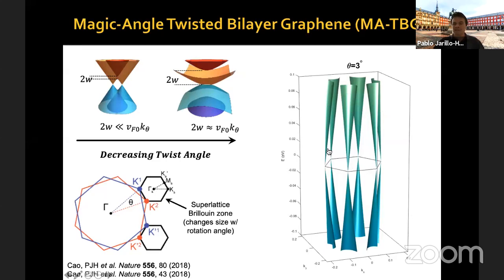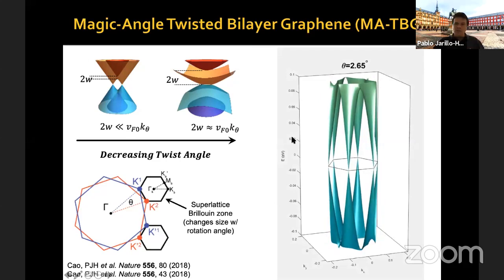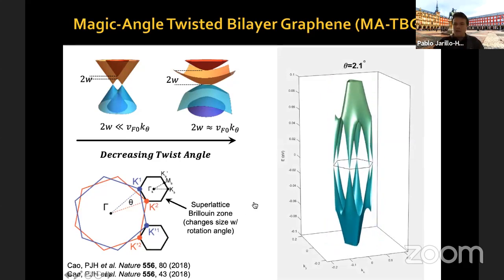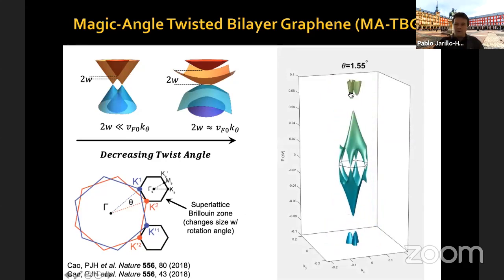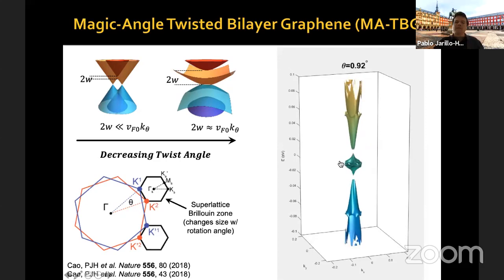So twisted bilayer graphene within this small energy window looks exactly the same as graphene. But as I run this video now, you're going to see how this electronic structure changes when you go towards small angles. So let me do this. As you can see, we have a set of bands now that is becoming separated from the more remote bands by band gaps. And these bands are becoming flatter and flatter. And now you see, they became very, very flat.